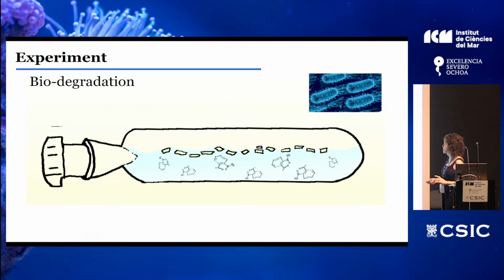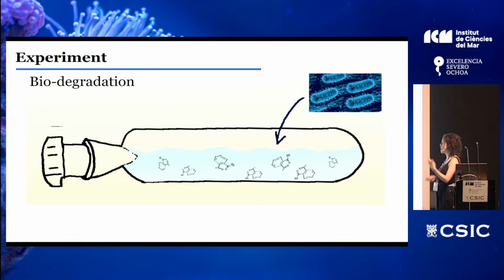of the experiment in which, once we have the leachate, the plastic is removed, and then we add a natural bacterial inoculum that we filter through 0.8 to remove traces, and we incubate this in the dark for a few days until bacteria reach the exponential phase. And once they reach it, then we stop the experiment and we measure again the same chemicals, the dissolved organic carbon, the dissolved organic matter that we have left, and we also do some microbial analysis that I will explain to you later. We also follow this experiment analyzing microbial abundance every day to follow the curve and know when they start to grow and when they stop growing.